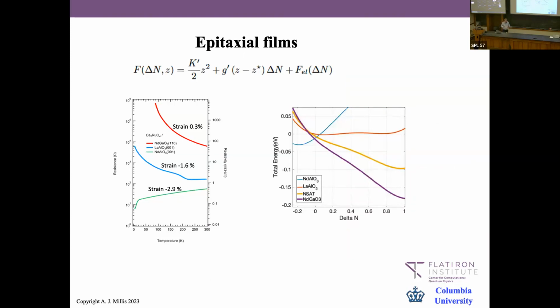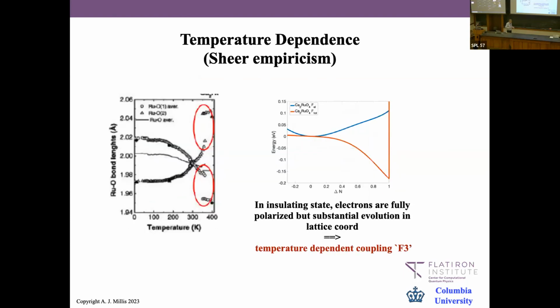You can do the same thing with films and more or less reproduce what's going on. We find that the energy is minimum nearly at 0 for this one. By the way, the color coding is bad: the blue one here is the green one here, the blue one here is the red one here, and the yellow one here is the red one there. Sorry about that, we're fighting my thermostat. But you can see you get essentially the same trends: very strongly insulating for these two, intermediate for this one, and always metallic for that one. So I think this gives us a reasonable handle on what's going on.